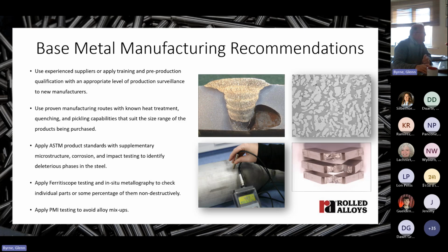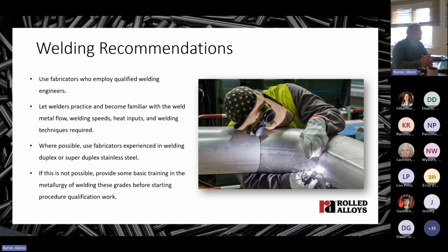Apply ferritoscope testing and in situ metallography to check individual parts, or some percentage of them, non-destructively. We've not mentioned this, but really apply PMI testing as well to avoid alloy mix-ups. All these stainless steels look pretty much the same, so you need to do that to make sure you're not mixing.